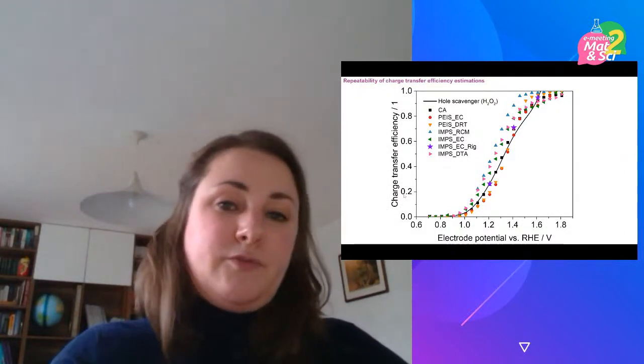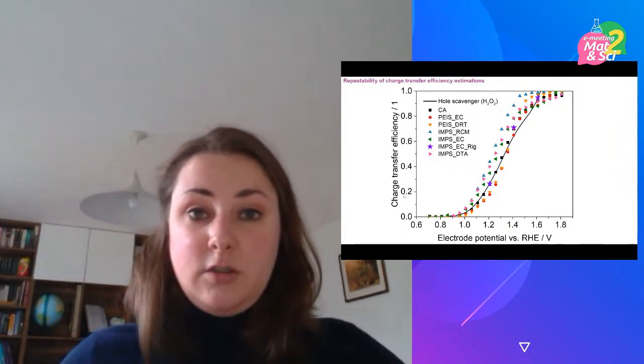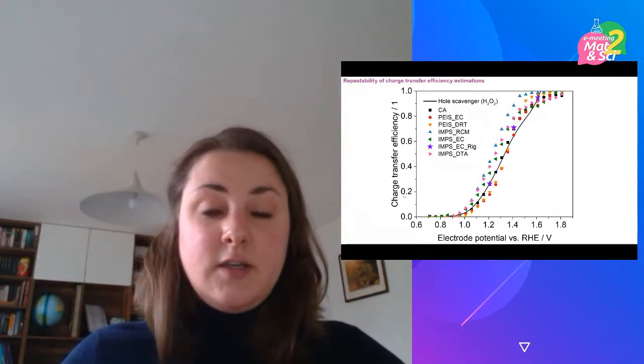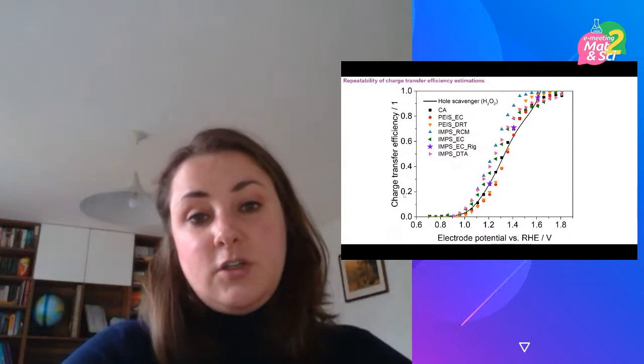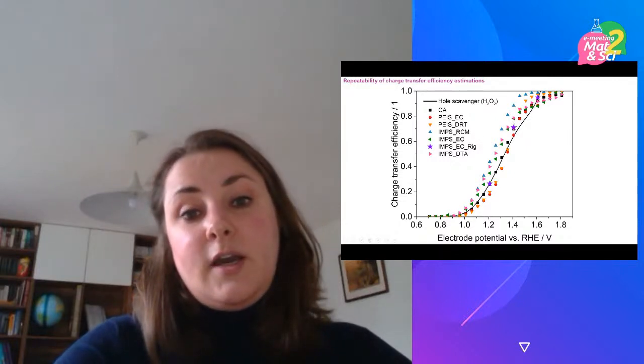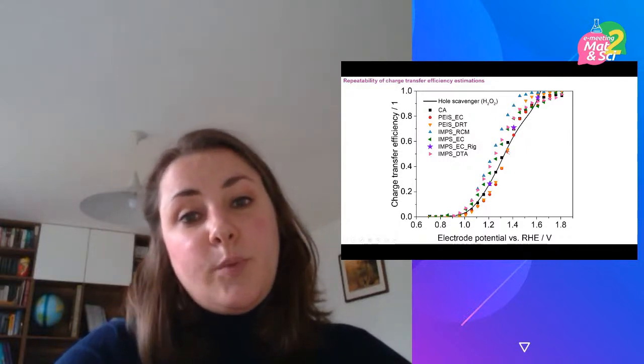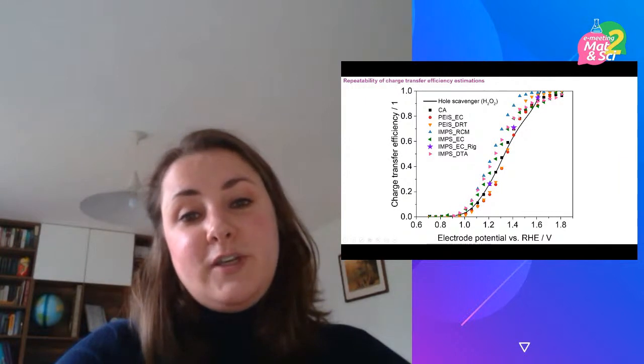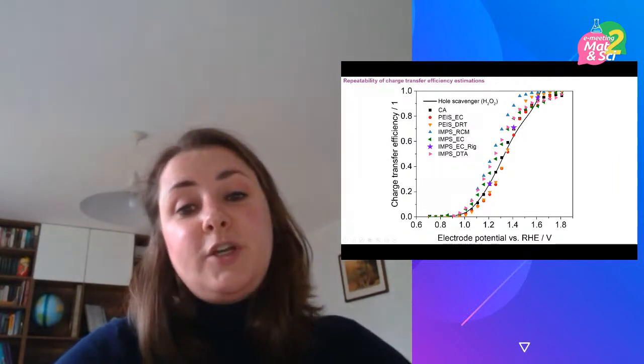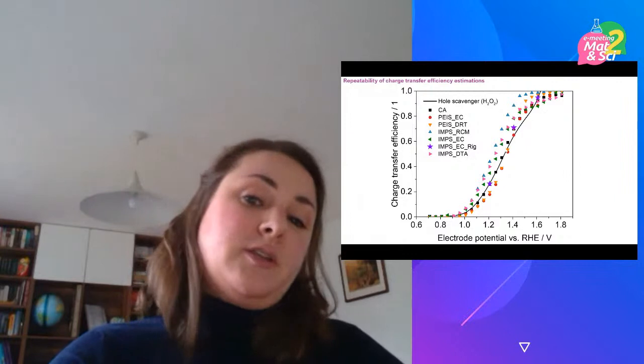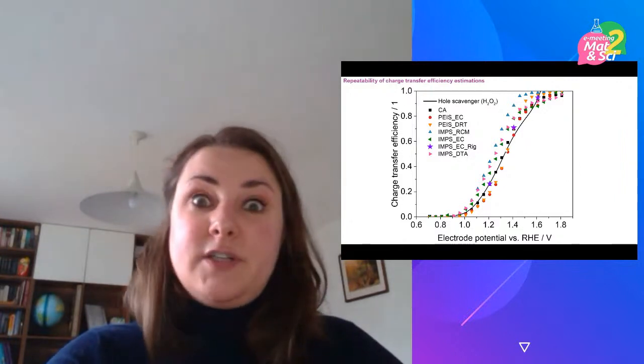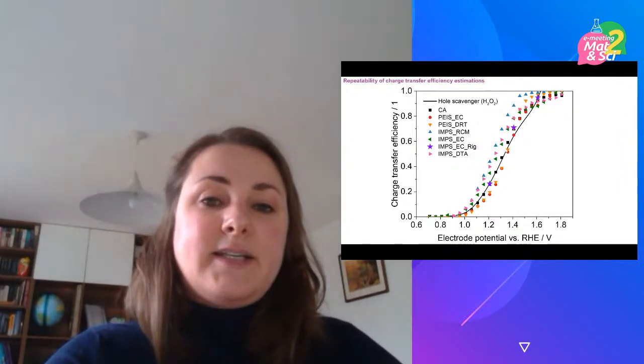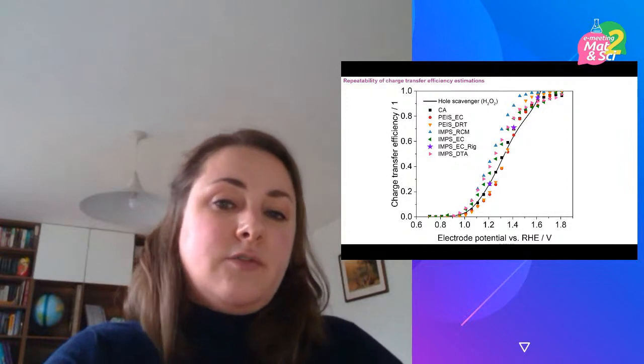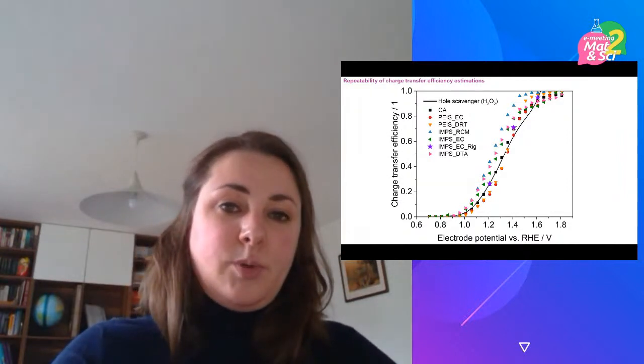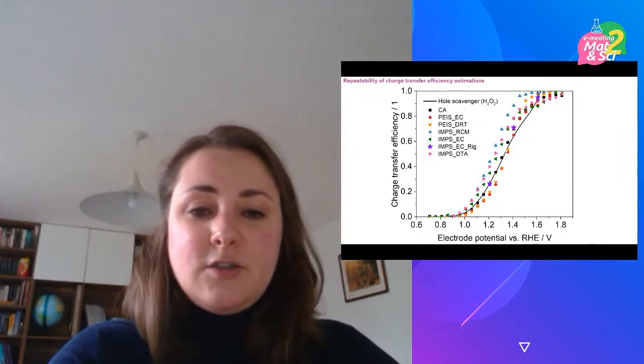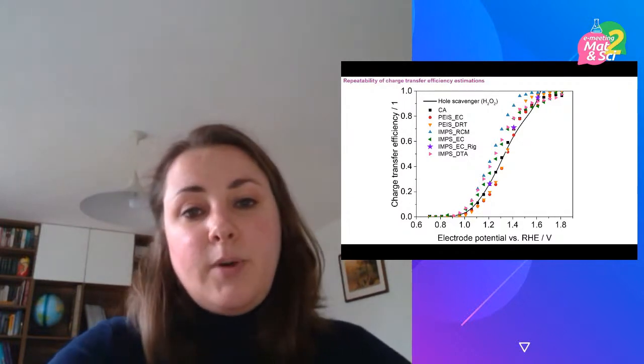So as you move away from the flat band potential, recombination losses decrease, but in that transition region, they are quite difficult to calculate. But probably I would say that any of these results would be good enough when it comes to putting this kinetic model into a multi-physics model to design reactors, because there is no significant impact of this on the predicted photocurrent densities, or at least their magnitude.